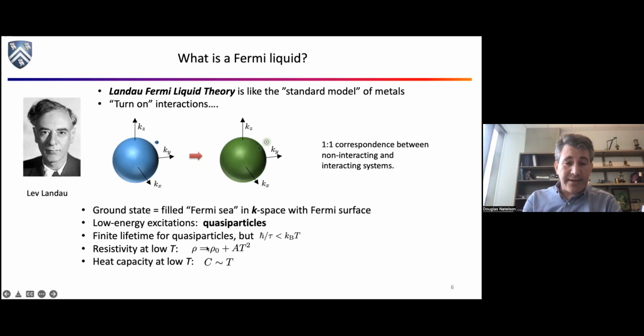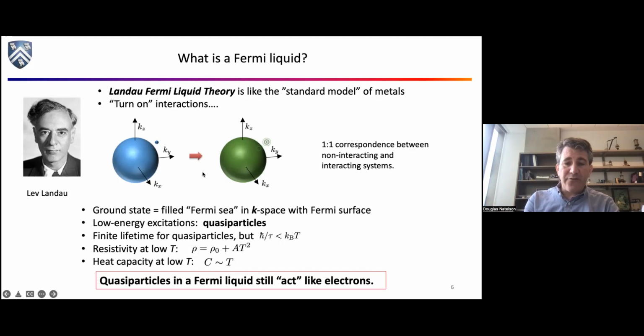And interestingly, the resistivity in this kind of a model still goes like T squared at low temperatures. The heat capacity still goes like T. So you can see in a Fermi liquid, which describes copper or aluminum or gold, the quasi-particles still act like electrons. You can really think about charge being carried by these discrete objects that have well-defined charge. They live a long time. And so that's kind of the standard picture of metals.